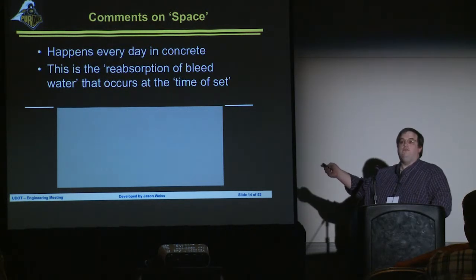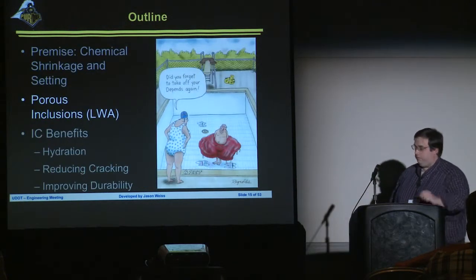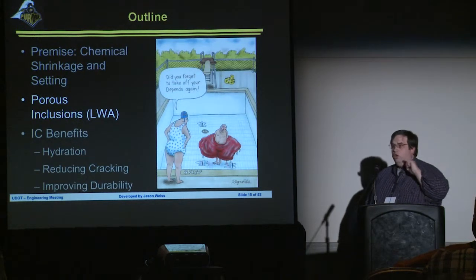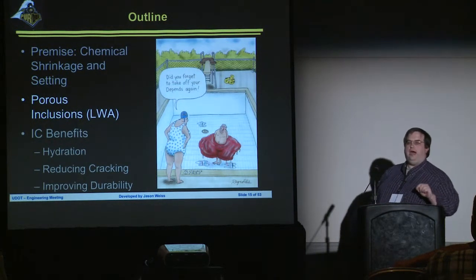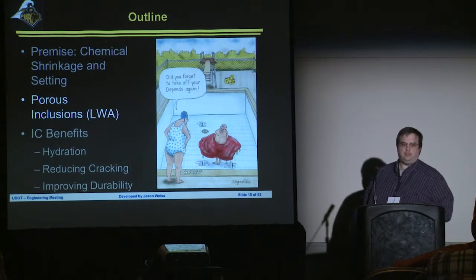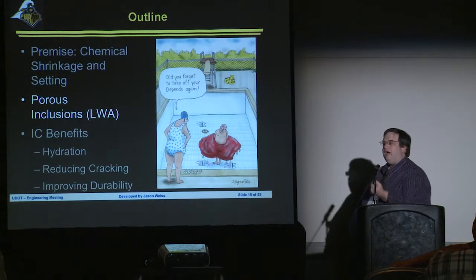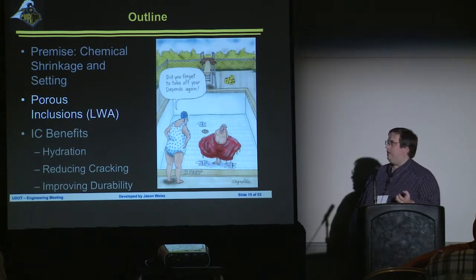All right, so this happens every single day, and it just so happens it happens at the time of set for the same mechanisms that I was talking about before. Now, we want to talk about ways that we can hide water inside of this system. And what we really worry about with our water to cement ratio is keeping the water to cement ratio low until the time of set. Because at that point, we want to lock the microstructure in place. We want to lock that porosity in place.